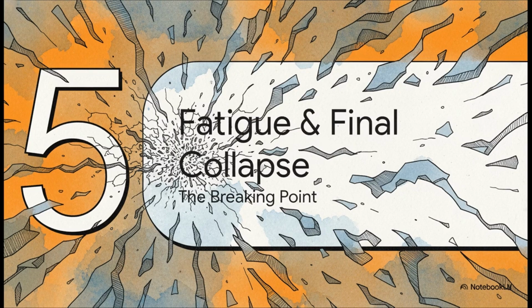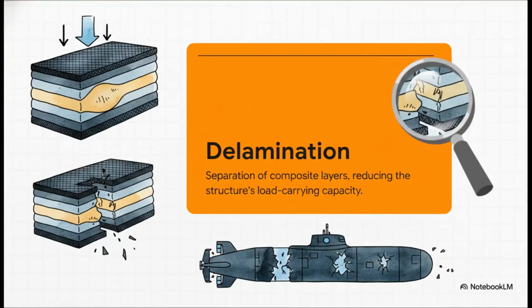Finally, Section 5, fatigue and final collapse. We absolutely must understand the concept of delamination here. Because wrinkles in carbon fiber form these soft, resin-rich pockets, they compress way more easily than the stiff carbon fibers around them. When the hull dives and is subjected to that immense external ocean pressure, these soft spots squish down. That causes the surrounding rigidly glued layers to literally pry themselves apart. This peeling apart of the composite layers, kind of like an onion peeling from the inside, is called delamination, and it absolutely kills a structure's ability to carry a heavy load.